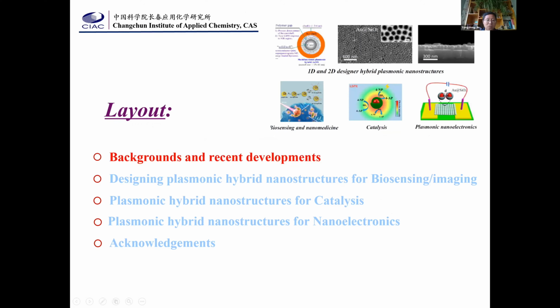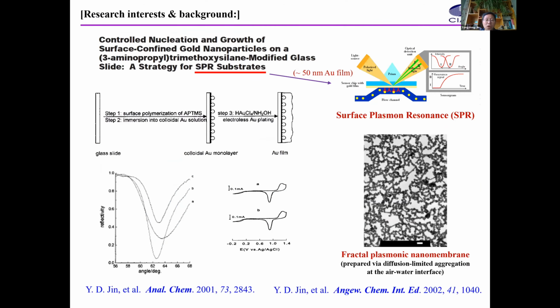So, layout. First, background. My interest in plasmonics began when I was a graduate student at the CIAC. My first work in the field was the development of a wet chemical route to prepare SPR substrates, that is about 50 nanometer thick gold film, usually prepared by vacuum vapor deposition. We also developed a method to prepare fractal plasmonic nanomembrane via diffusion limited aggregation at the air-water interface.